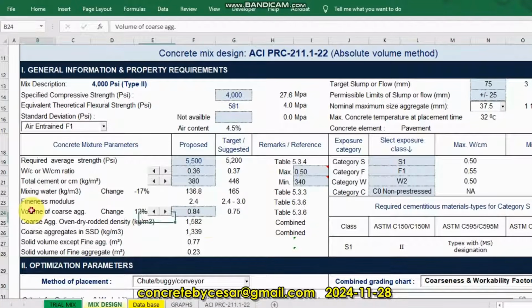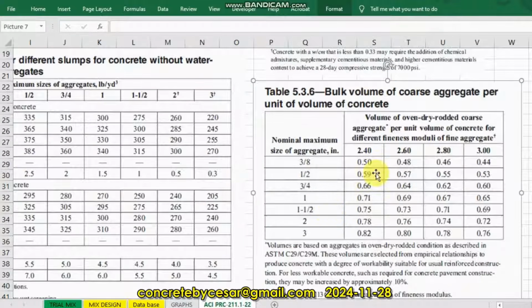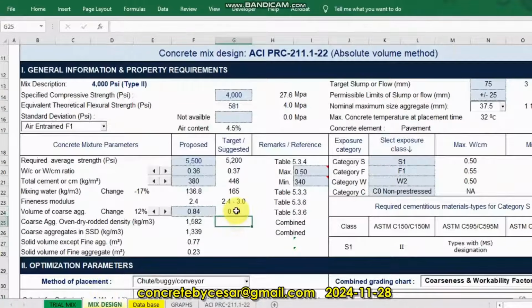So next, the volume of coarse aggregate. Referring to the table again, that will be 0.75 using the nominal maximum size of aggregate 37.5 with a fineness modulus of 2.4. You can double check it from this table. So 1.5 inch is equal to volume of coarse aggregate 0.75 at 2.4 fineness modulus. I just want to show you where it came from.